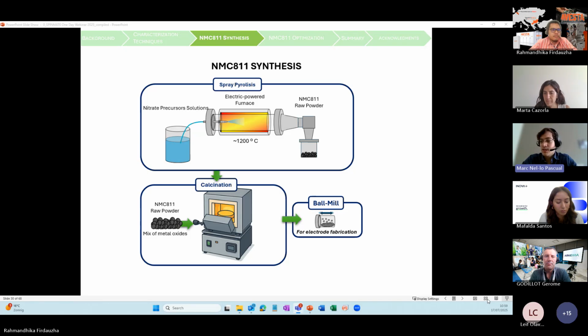But it's true that, for instance, in our case, ball milling, I think it was good to do it. But if you are using co-precipitation, there are secondary particles that are spherical, and even with some low energy, you have to look for not breaking those particles. So you won't be affecting crystallinity, but you could affect the performance of the material with the ball milling in the end. So it's something to check that you are not breaking these particles.